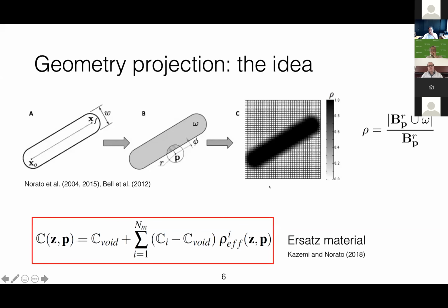And as we do in density-based optimization, for instance, we take that density field and define an ersatz material for the analysis. In the particular case of multi-material lattices, we have to account for the fact that we have multiple materials, so we define an effective density per material per bar, and then we add constraints to the optimization that make sure that at most one of the size variables corresponding to each material for each bar is 1, meaning that one strut can be made of just one material in the optimal design, and that all the size variables for the materials are either 1 or 0.